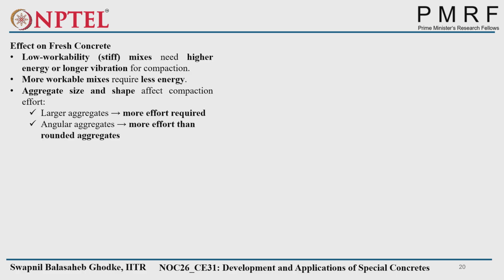So more workable mixes require less energy, obviously. Whichever has the higher slump, less energy is required to get proper compaction. If we still provide higher compaction, the segregation and bleeding will happen.